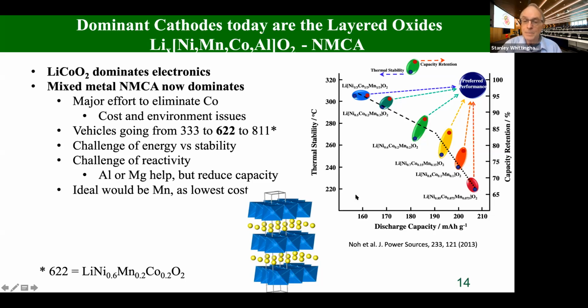here, this thermal stability is only 220. Clearly, we're not going to heat the battery up to these temperatures, but this instability is a measure of how fast these materials react with the organic solvent, so are reflected in the capacity retention. So our goal is to get to this upper box here, highest energy density, highest stability, and retain capacity forever.